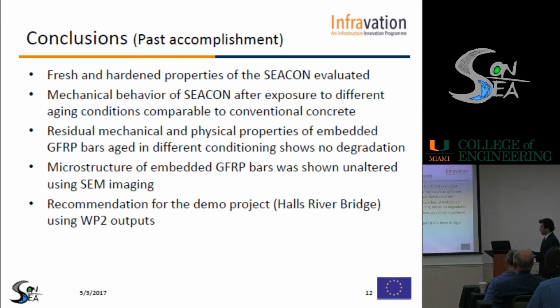So the fresh and hardened concrete properties, WP1 went into details, but based on the compressive strength results that we got, seawater concrete after 2 years performed better than the conventional concrete. So the mechanical behavior of SEACON, as I mentioned, was actually better compared to the conventional concrete. The mechanical and physical properties of the embedded GFRP bars, again, we were expecting to go down, but we saw better results for seawater concrete. And then microstructure, SEM imaging didn't show anything, so no impact on the microstructure of the concrete due to using the seawater concrete. And then for sure, we are using all these as recommendations for our demo project, which is Halls River Bridge, and we're all going to see it tomorrow.